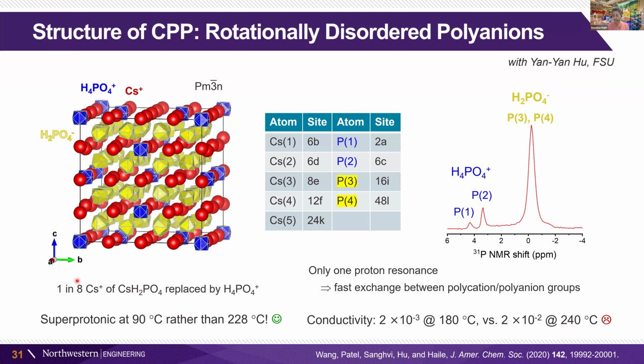And again, they are tetrahedral units, but because they're undergoing this reorientation, they look like these funny shapes for the polyhedra. And we can see in the NMR results that when we have this structure, we can see the proton NMR peaks for the polyanion groups. They overlap significantly. They're not resolved. And then the two polycation groups have their proton signals as well. We can't differentiate all the different types of protons in the system, but I'm sorry, these are the phosphorus NMR. So we can see the phosphorus shifts, and we can't distinguish the two different phosphorus groups, the P3 and the P4, which are the polyanions, but we can distinguish the two phosphorus that are the polycation groups.